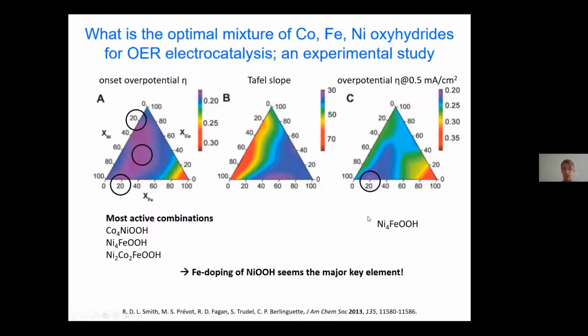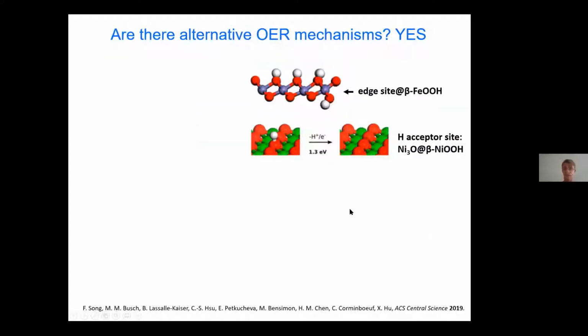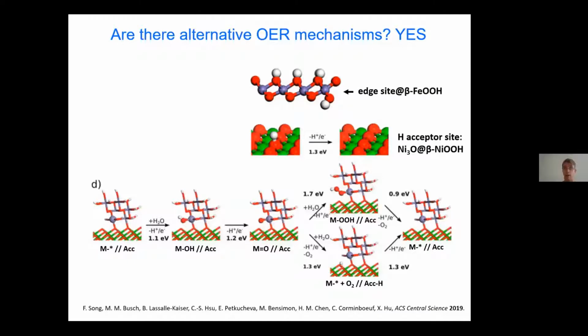So to explain the activity of these bimetallic systems, we can look to alternative OER mechanisms. So alternative, not mononuclear or single site, but binuclear or bifunctional. So here is an example, the earliest example of a bifunctional route for these metal oxyhydroxides that appeared in literature. So we have an active edge of iron oxyhydroxide that is combined with an acceptor site.